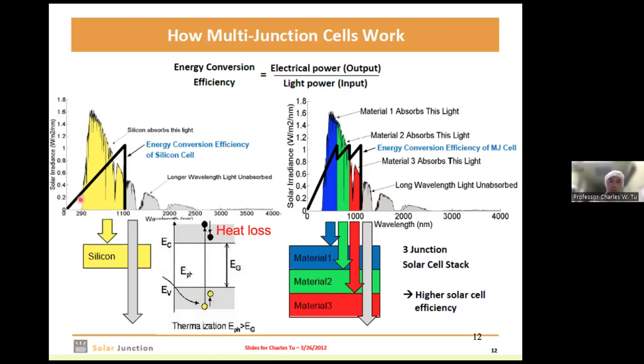And to improve this efficiency, people use multi-junction solar cells. So here we have 3 junctions. Okay, the top has a larger band gap, so the high energy photon is absorbed. Middle and low energy photons pass through and then get absorbed in the middle, and the low energy photons are absorbed at the bottom. So you can see that I have strong efficiency here, and then the conversion efficiency starts to decrease. But I have a middle band gap, so it increases again, and then lower and increases again. So you can see this conversion efficiency for multi-junction solar cells should be much higher than just a single junction solar cell.